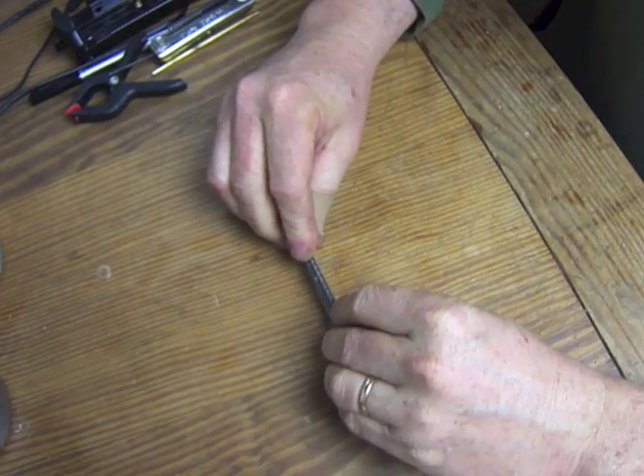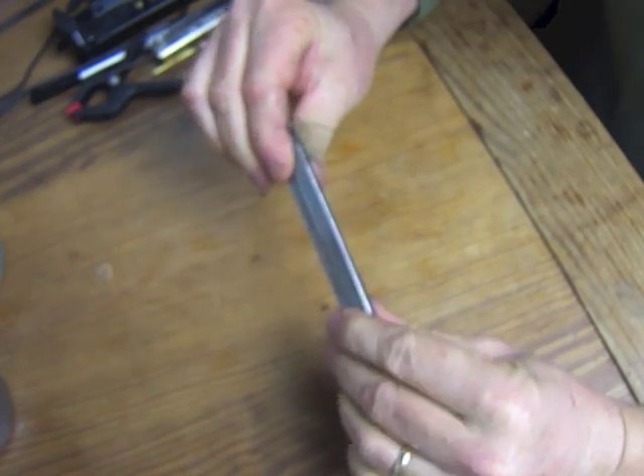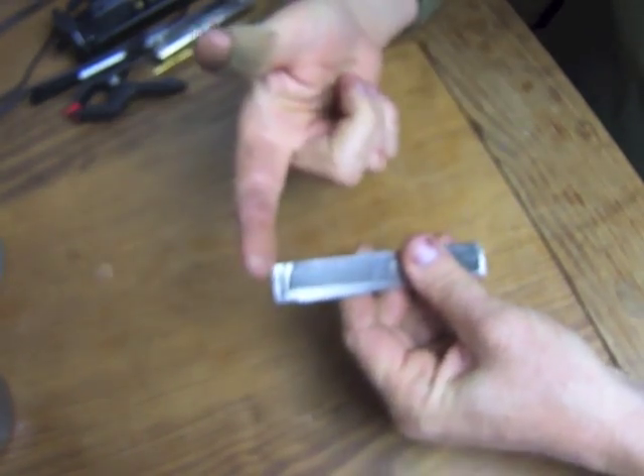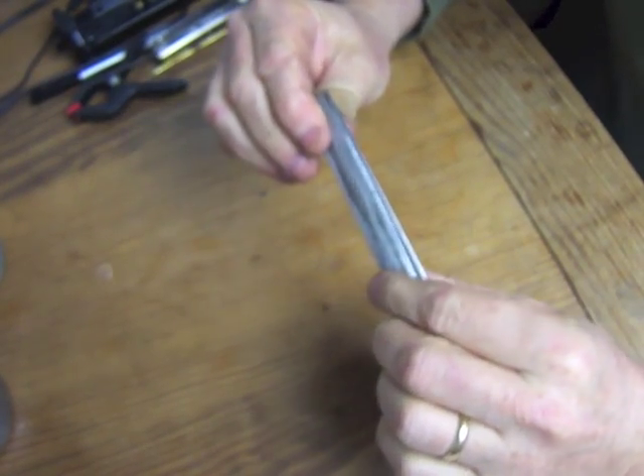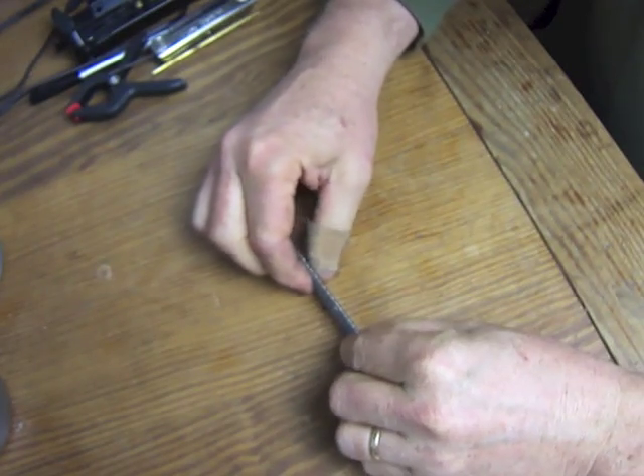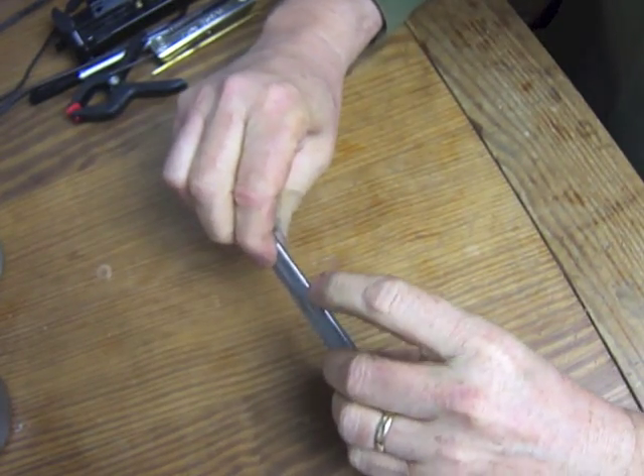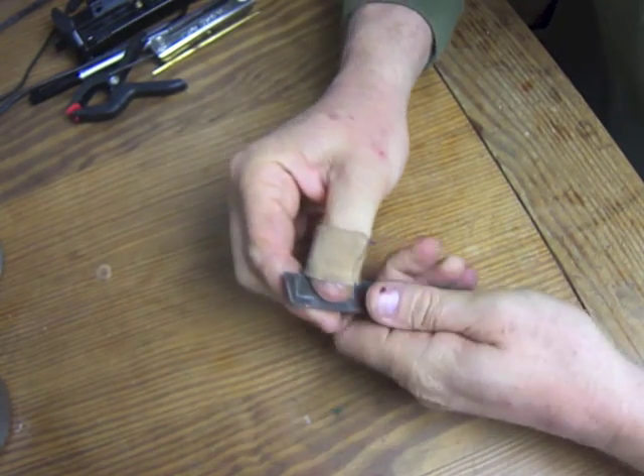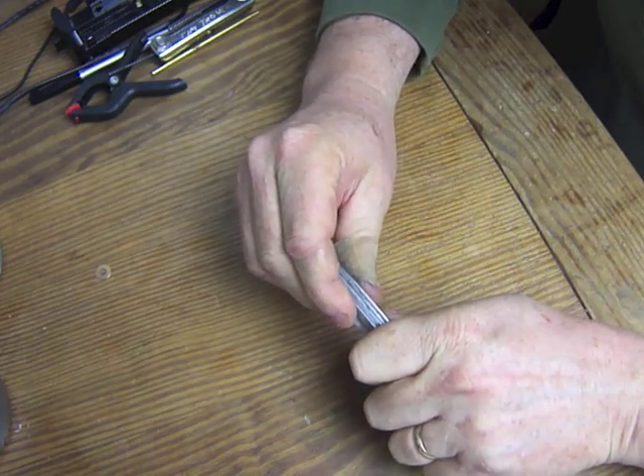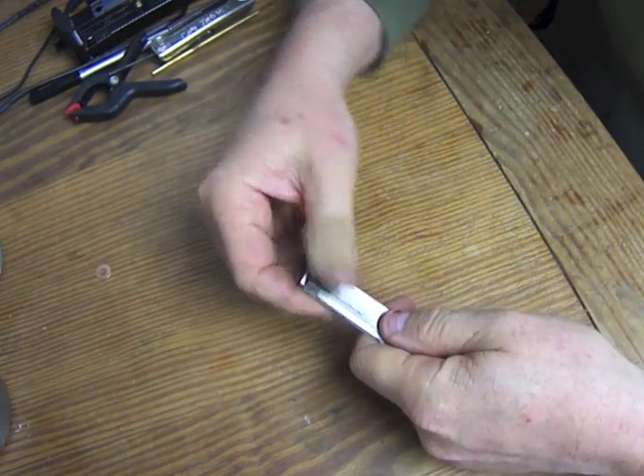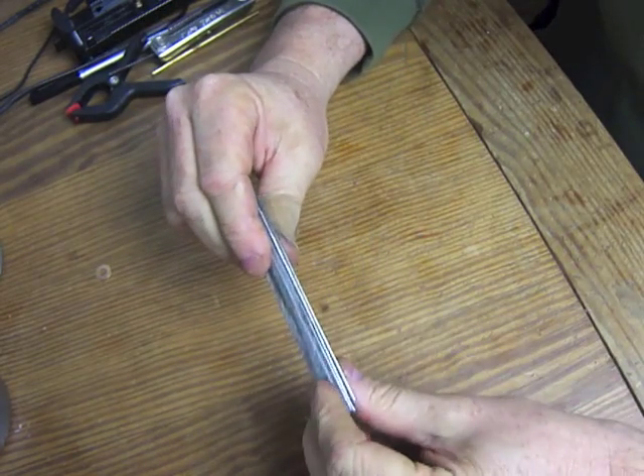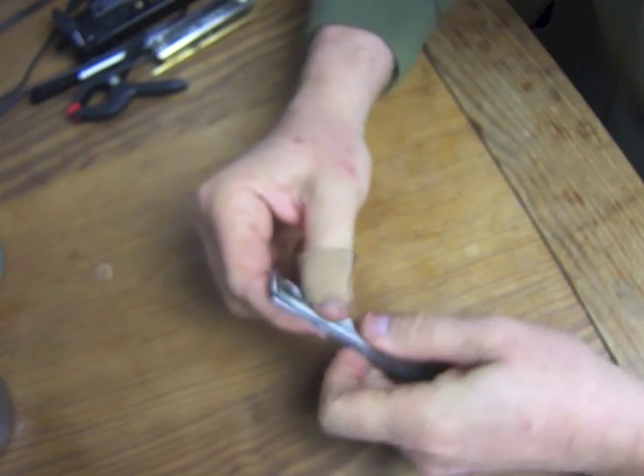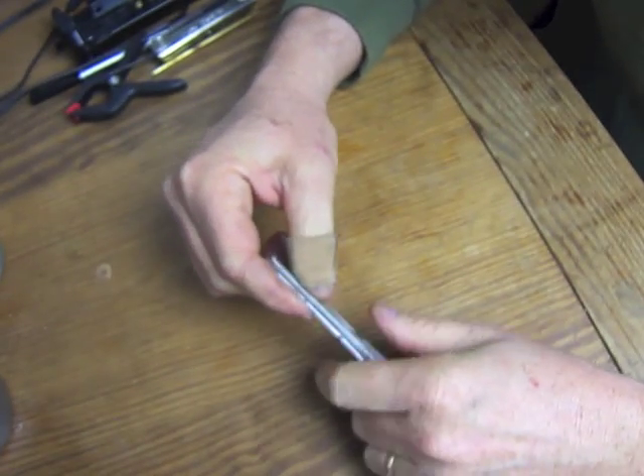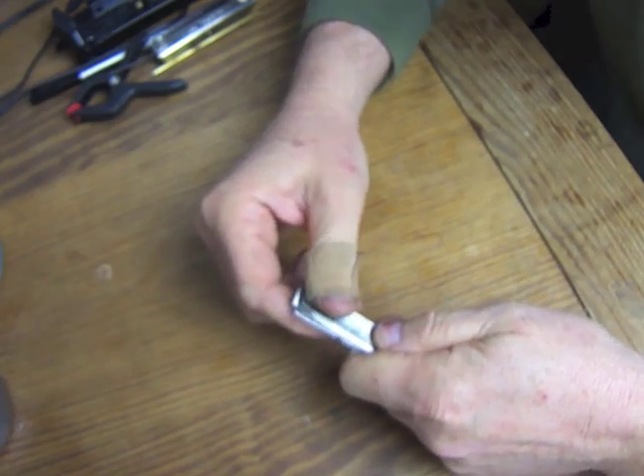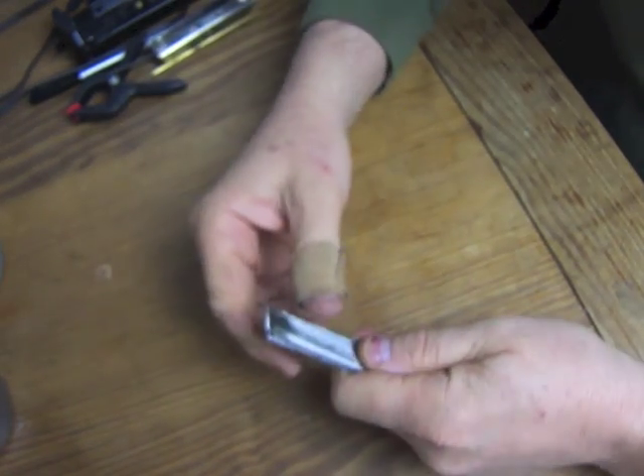So for that, if you have a welder, you tack weld the ends. Sometimes some people also tack along the length, or if you don't have a welder, or if you have one and you're just doing something small, you can also wrap wire around it. And I use a wire that's softer iron wire that's steel, that's used for holding up suspended ceilings and stuff like that, and just wrap it around and twist it real tight.